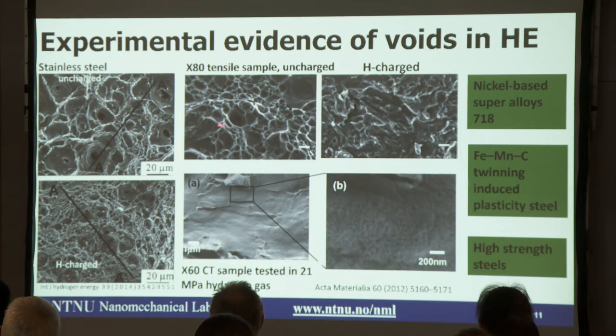So we have looked at the pipeline steel. In the case without hydrogen, we have very well-organized dimples. But with hydrogen charged, we see quasi-cleavage features, but there are still some dimples. For the X60 pipeline steel, even on the cleavage facets, if you go to higher magnification, then we also see nano dimples. So we have seen dimples on many other different materials, including nickel-based superalloy 718 and high strength steels. I'm not going into the details here.